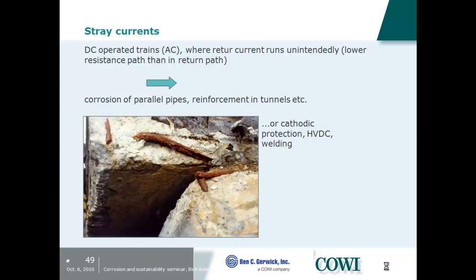We repaired a wharf after the earthquake, and we had to extend new bars with old bars that were coming out of the old concrete that had some chlorides in it, and we were concerned about corrosion developing, the ions being exchanged between the new and the old. So we put a piece of zinc in there, tied it to the rebar. Yeah, Victor has this system that was developed some years ago with these small zinc anodes.